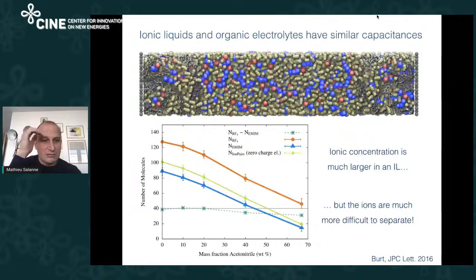You see that in the pure ionic liquid, we reach 125 and something around 90. But in the system where there is a lot of solvent, we reach 50 and 10. And so the difference is always the same. And so what happens is that the capacitance will always be the same. And in fact, the story behind this is that in ionic liquids, you have more ions in the system, so you expect this to be good. But it's much more difficult to separate them because you don't have a solvent that allows to split your ion pairs. And so in the end, the capacitance is no better.